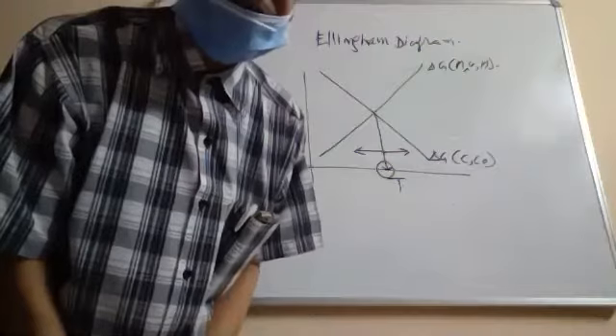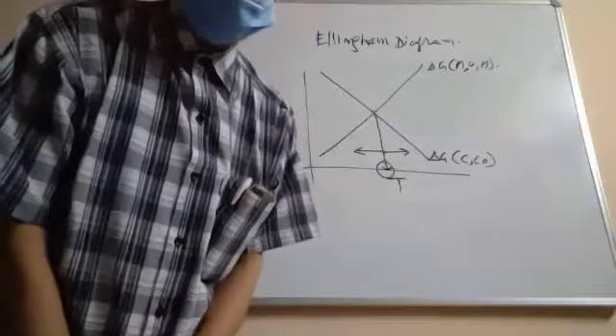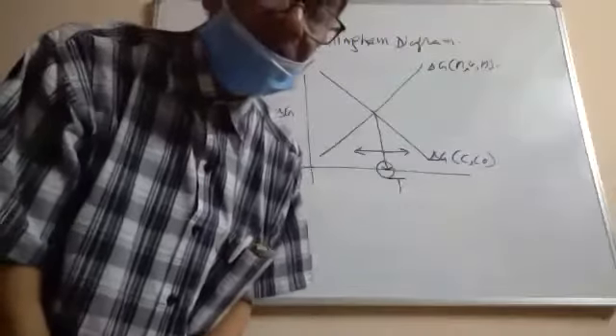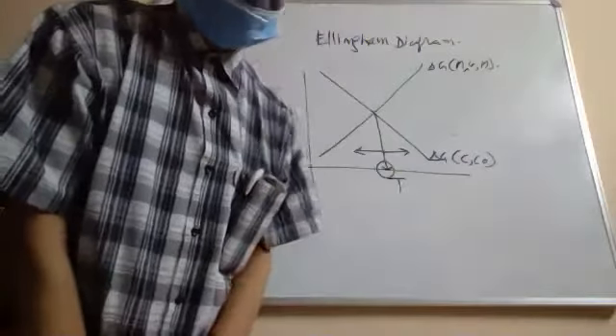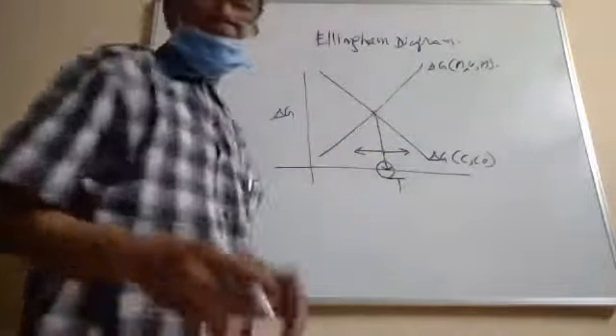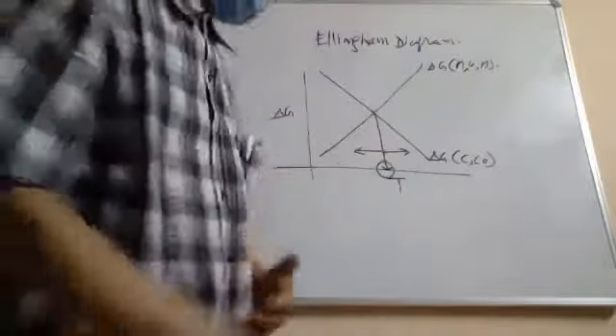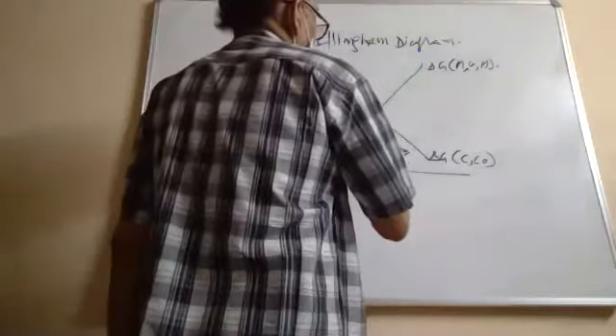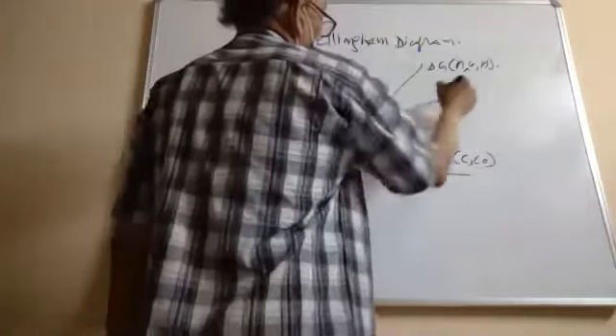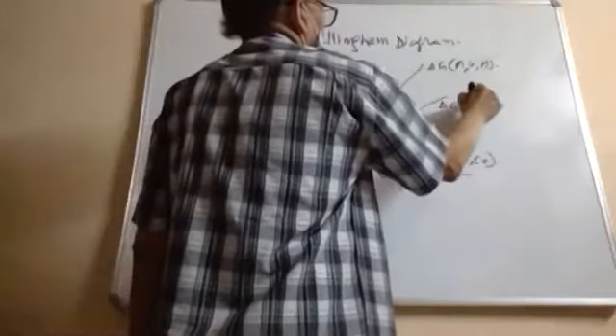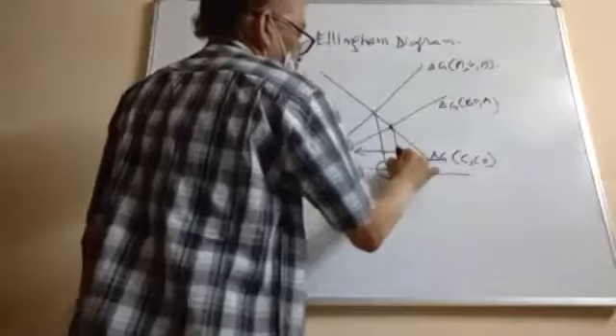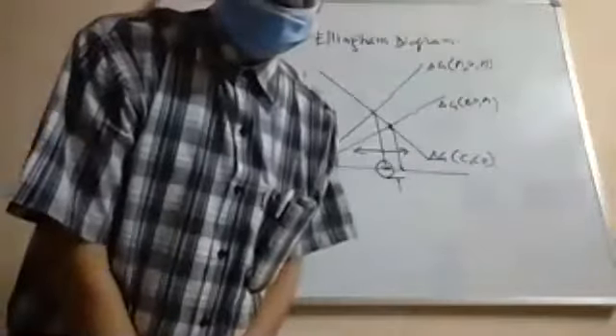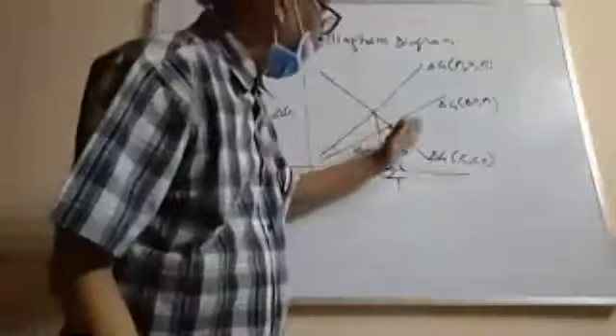Because the oxidation of carbon to carbon monoxide is not thermodynamically more favorable than the oxidation of the metal. So if you now do this for multiple elements, you will see different materials having different slopes. For example, something will have a slope like this for the metal to metal oxide, in which case the crossover temperature is high. So different metal oxides have different crossover temperatures, and that's the reason why some oxides take extremely high temperatures for the reduction to happen. Am I making sense here, folks?